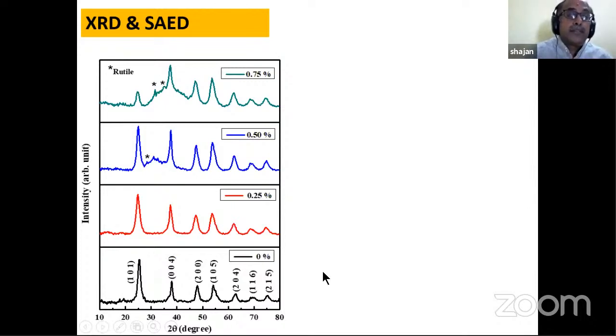Now, if you see the XRD and electron diffraction images, you can see the difference. So this is for the pure aerogel that is indexed here. Now I am adding 0.25% of MOF. There are no major changes happening. But when I go to 0.5%, you can see some additional peaks coming in. And when I increase to 0.75%, there is a significant change, and broadening of the peaks takes place.